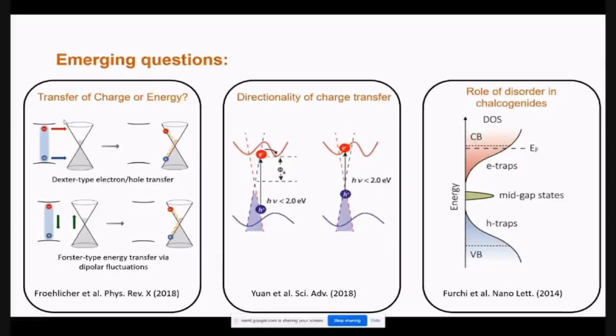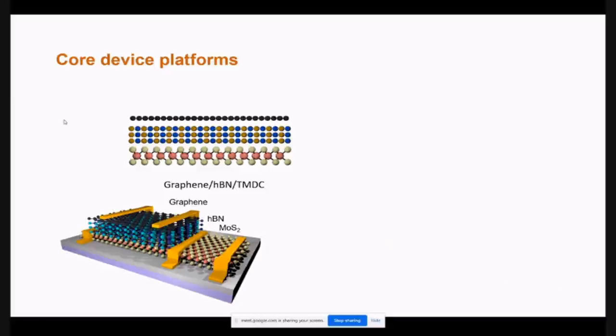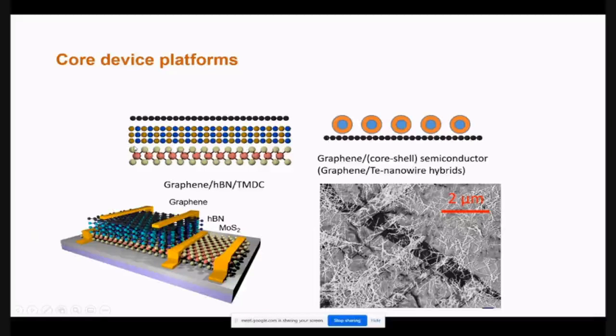I will not go into the detail now. We have been working on various device structures like the graphene, and then we put a layer of boron nitride in between the graphene layer and the chalcogen layer. We wanted initially to see if we can get energy transfer, but that didn't work out well. But we have been working on nanowires, on graphene heterohybrids, and so on and so forth.